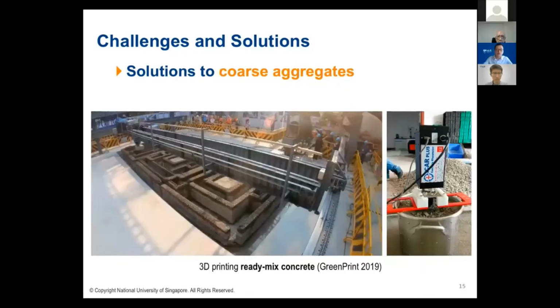Okay, so another challenge is how to include coarse aggregate in the printable concrete. This is extremely challenging because the coarse aggregate will reduce the flowability, will reduce the rheology a lot. And last year, one Chinese company invented this gantry type 3D printer. They mentioned that they can print a ready-mix concrete.